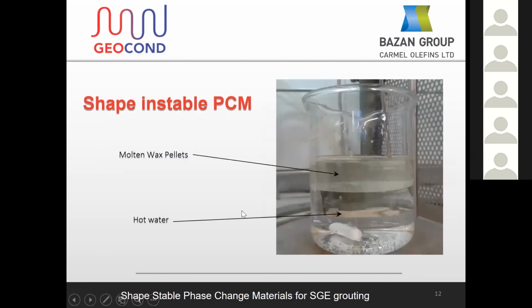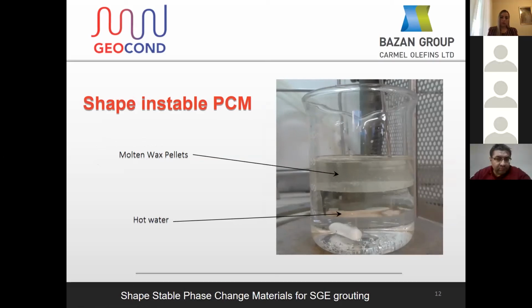Shape instability of PCM can be illustrated by a simple comparative experiment. If we take a classic organic PCM, pelletized paraffin wax with a melting point of about 60 degrees, and we put granules in hot water at a temperature of about 80 degrees, the pellets, having a density lower than the density of water, will float on the surface, gradually melting.